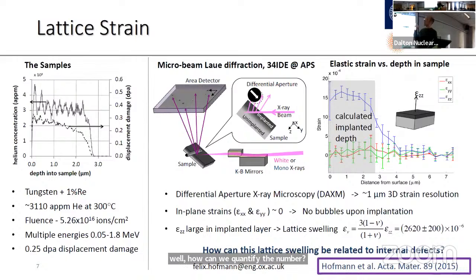So we thought, well, we can't do it with TEM, so let's look at other techniques. And what we resorted to is X-ray diffraction. This is a technique called microbeam Laue diffraction, which allows you to measure the full elastic strain tensor with micron resolution in all three directions in samples.